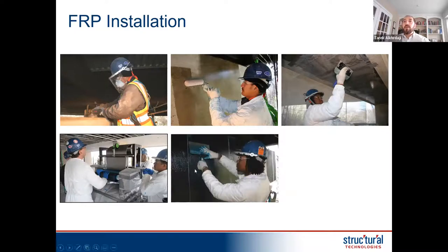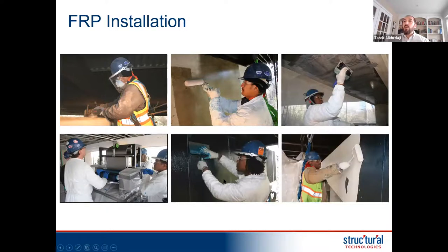Once you bring that saturated fabric, you attach it to the surface, you make sure you have no voids behind it, you know, remove all the voids. And once it's cured, you can apply a coating, and it could be, you know, anything really. There's a lot of different coatings that are compatible with FRP, because once it's cured, it's really like a hard polymer. So you can apply an acrylic-based system or any other system, stucco, cementitious material, even, with any color. So it's very easy to hide.